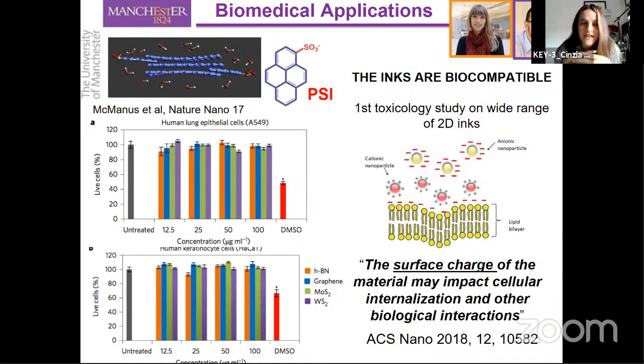And these results were actually very interesting because not only do the cells not die, but we observe a very strong cellular uptake, meaning that the material can penetrate the membrane. And so this opened up a possible use of our inks for drug delivery and related applications. So we started to look into the field. Obviously, this is something completely new for me. And we realized that typically cationic nanomaterials are preferred for this kind of application because they can better interact with the negatively charged membrane. In our case, however, our materials are all negatively charged because the surface charge is given by the sulfonic group.